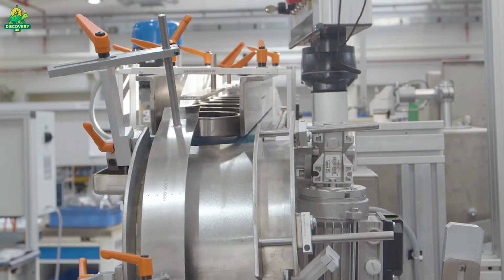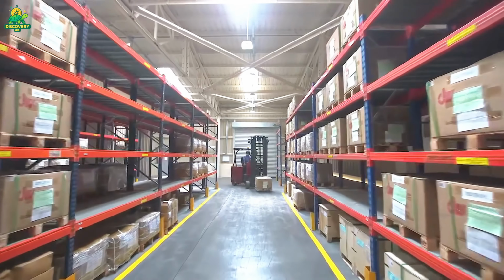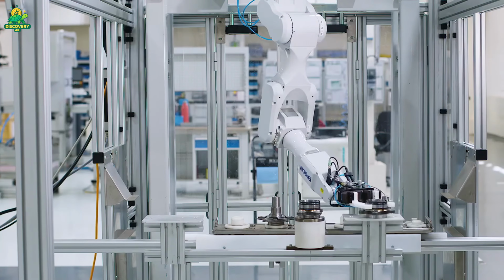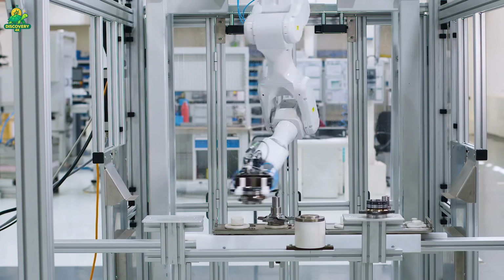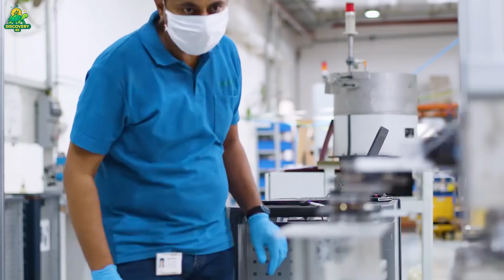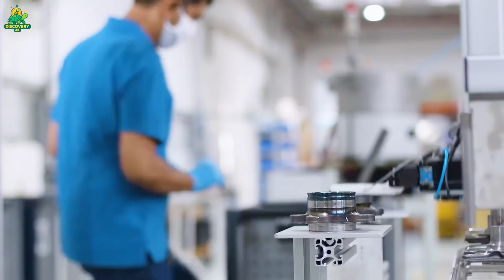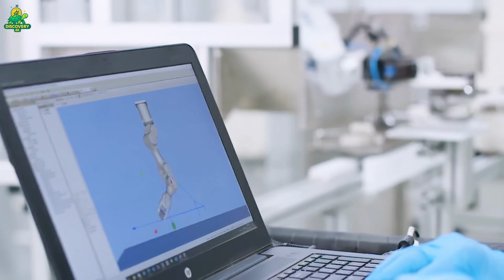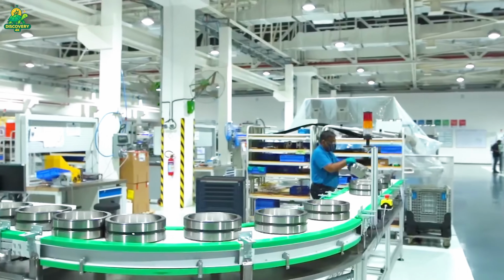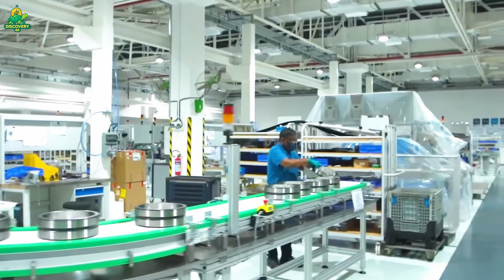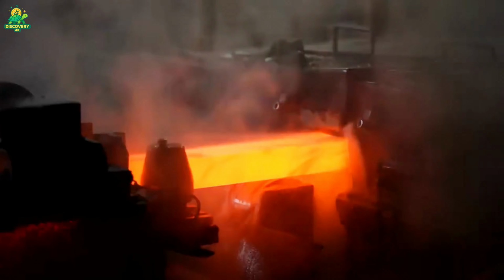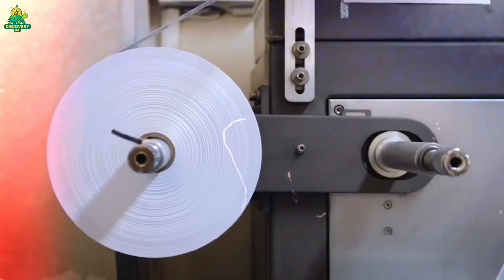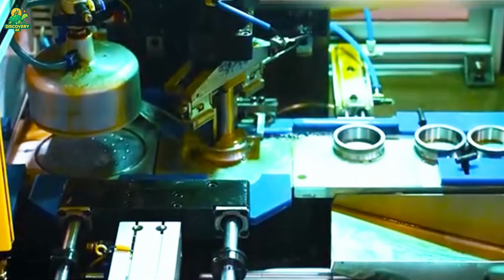Steel wire is cut into tiny cylinders, heated and pressed into rough spheres using high-speed presses that produce thousands per minute. These balls are then heat-treated and ground in rotating drums, filled with abrasive paste until they reach a perfect sphere shape. To test precision, engineers use laser gauges capable of measuring roundness to one millionth of an inch.